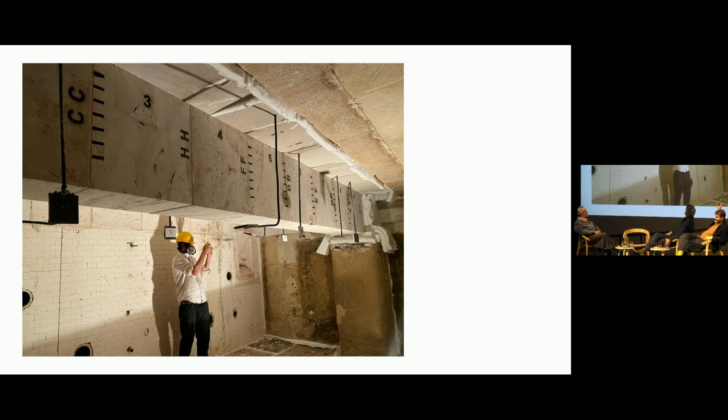This was the first big fire test. It's an 8-meter span beam carrying two 10-ton loads. It sat on a Friday afternoon outside Paris for what should have been a 1-hour fire test. It survived for 3 hours, making those French fire engineers very annoyed. And eventually it didn't collapse. They closed it down.